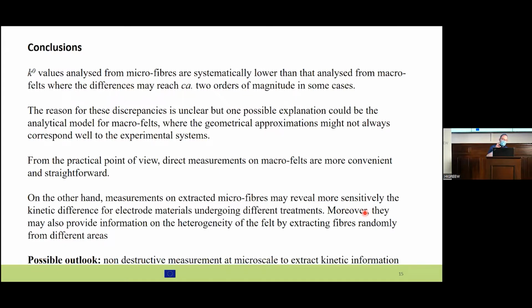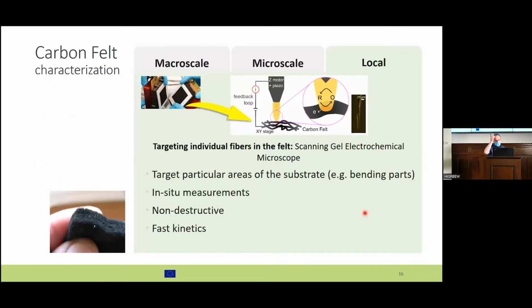I just mentioned that microfibers from felt can be extracted. We take the fibers and if we are good experimentally, we can glue them and do the measurement accurately. Another way we developed, one potential innovation linked to HIGREEW, is a technique derived from scanning electrochemical microscopy in order to contact the material without destruction. And so we do local measurement. This could be a good tool for quality control of the material, for graphite. I'm not sure it's useful, but for carbon paper or some other material. So this is just one potential innovation coming from the project.